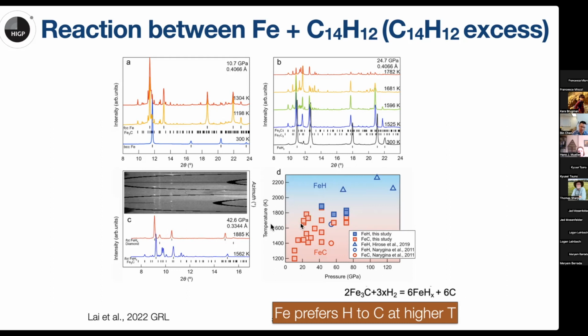So we performed a series of experiments, and we found this type of phase diagram. At a higher pressure, the iron hydride may be more stable than iron carbide. And when the iron hydride is more stable, basically hydrogen would kick carbon out from the iron carbide phase to form diamond. So those will be this reaction. That means the iron will prefer hydrogen to carbon at a higher temperature in our experiment.